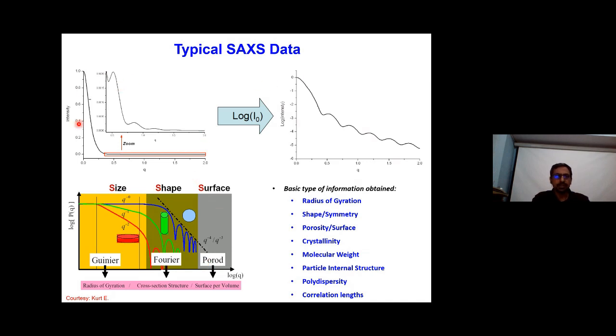A typical SAXS data, what I told you, is intensity versus Q, and people plot it in the form of log I of Q versus Q to see these features better. Now, what information can you achieve from there? I can take this data and start pulling out information from it. The information which can be achieved is size, shape, surface area. Essentially you can achieve radius of gyration, you can achieve shape. If the sample is porous, you can obtain porosity, you can obtain crystallinity in the sample, you can do absolute intensity measurement to get the molecular weight of the sample, you can find out the polydispersity, you can find out the correlation length, and so on and so forth. These are the sorts of information you can start retrieving, and this has to be done by some bit of analysis.